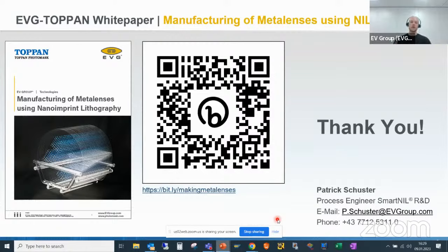So typically we go with a residual layer between 20 and 30 nanometers, because if you want to etch this into your substrate, of course, it needs to be as low as possible. But if it's too low, you might get, for example, adhesion issues for very complex structures. The good thing is we can control the residual layer because the structures themselves need a certain volume of the resin. And with spin coating, we can achieve a very uniform coating of the resin, between, let's say, 30 nanometers up to a few microns. Everything which is not consumed by the structures is then just the residual layer. You just need to subtract to get the remaining thickness.